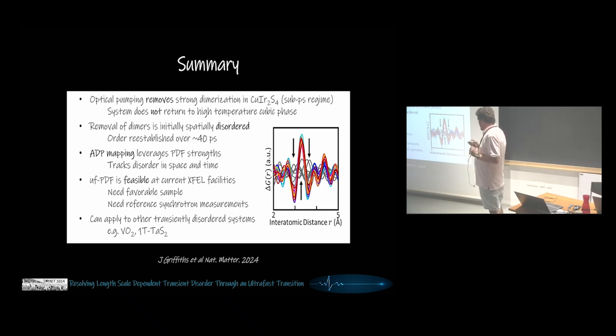So here's the summary. Optical pumping removes strong dimers in this test system in a sub-picosecond regime, which we haven't probed. The system does not return to the high temperature metallic cubic phase. The removal of dimers is initially spatially disordered. So basically different regions do not talk to each other initially. But order reestablishes over the 40 picosecond time scale. The atomic displacement parameter mapping leverages the PDF strength and actually tracks disorder in space and time. So this gives you the vehicle to extract this type of information.